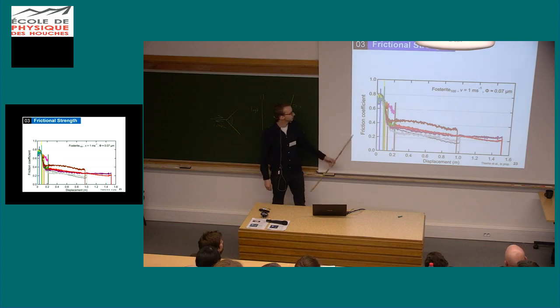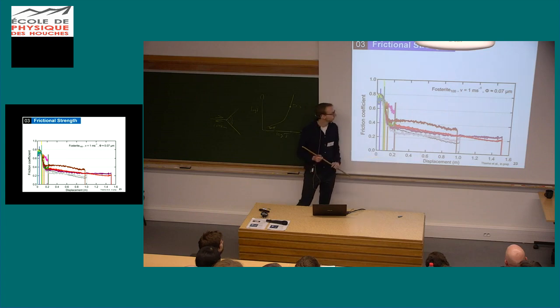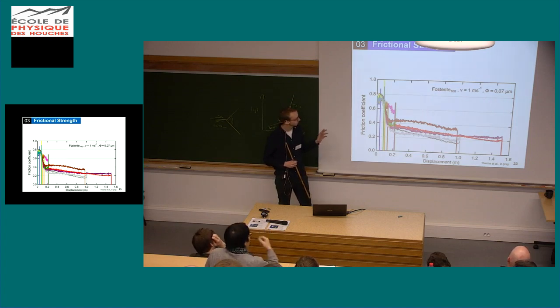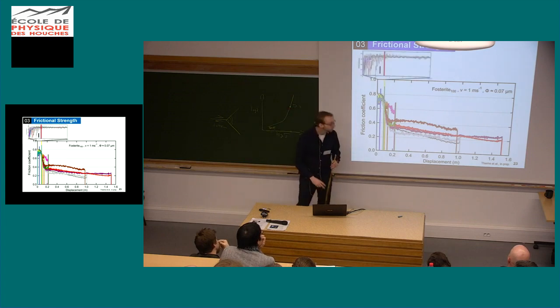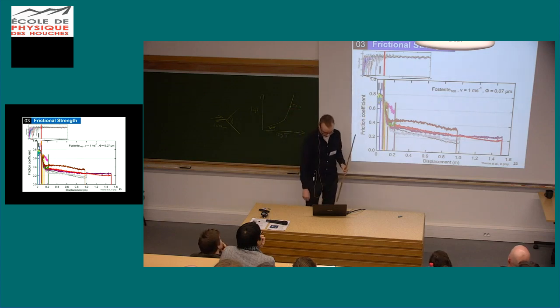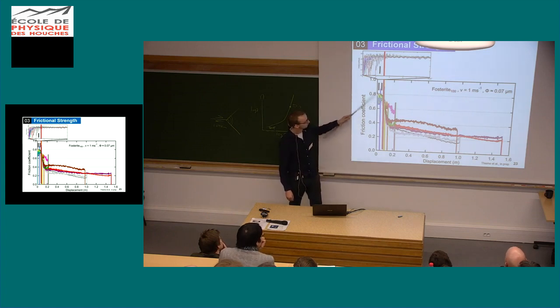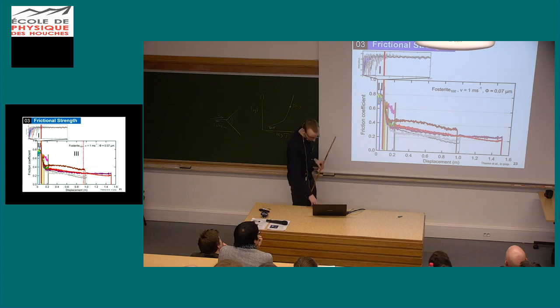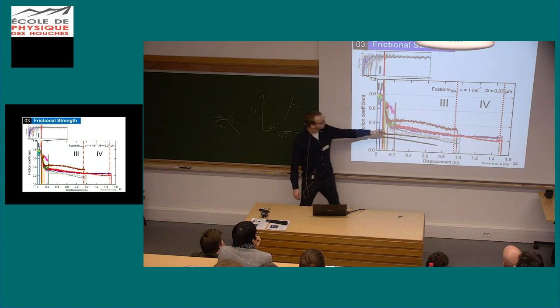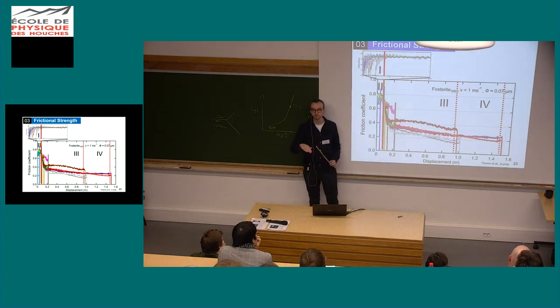After doing those experiments, you get mechanical data — in this case not stress, but a friction coefficient plotted against displacement. These are all the experiments for the synthetic forsterite deformed at 1 meter per second with a grain size of 70 nanometers, and they all follow the same stages. There's a very initial phase where the friction coefficient quickly rises, then a second phase where it slowly gets to a maximum of around 0.7 or 0.8, achieved upon reaching target speed. Then a third stage where the friction coefficient quickly drops, and a fourth stage where you have a quasi-steady state with slowly decreasing friction coefficient in a more or less linear nature.